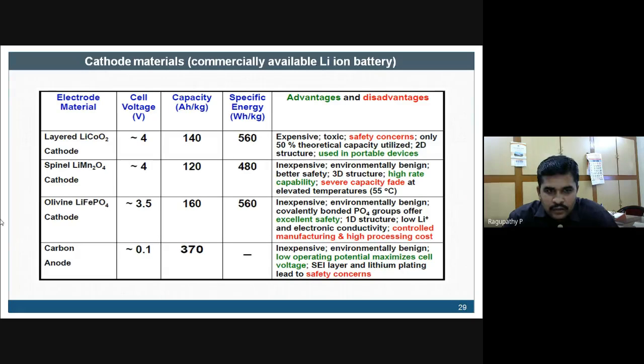On the other hand, if you look at spinel, another wonderful cathode material, you could see complete lithium extraction is possible, but the capacity is slightly less, here 120 for this compound. Then there is lithium iron phosphate. Iron is much cheaper compared to these two. But again there is a problem: poor conductivity. So you need to improve the conductivity of this material, and that again involves processing cost. So we need some kind of optimized selection of the active material.